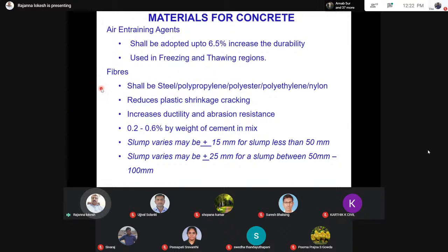And the next parameter that gets into the concrete is the fibers. There will be initial shrinkage cracks since we are not going to provide any reinforcement in the PQC. So it is advisable, as during the process of hardening there will be some shrinkage cracks. These shrinkage cracks can be reduced using steel, polypropylene, polyethylene, and nylon fibers. This will reduce the initial plastic shrinkage cracks and increase the durability. The weight of fibers can be 0.2 to 0.6 by weight of mix. This is dependent on the slump of concrete.